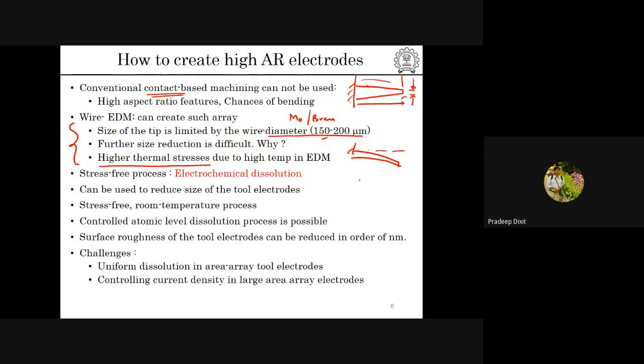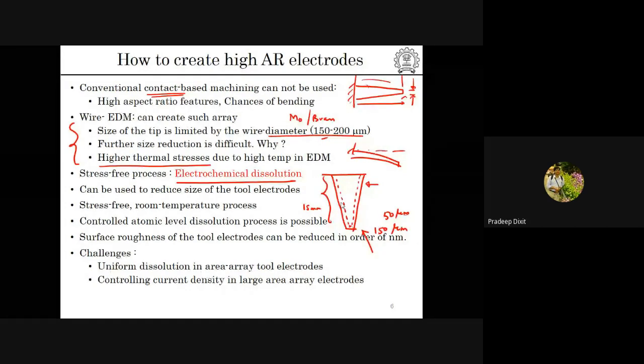So what we thought is that we will first get this kind of tool electrode by the wire EDM process, and then we will go for electrochemical dissolution. The idea here is that you fabricate the tool electrode. I'm just showing you a single tip. For example here, it could be 150 micrometer, and this could be 15 millimeter. After some point of time, if we do a controlled electrochemical machining and remove, let's say, 50 micrometer from each side, we will be removing this material by electrochemical dissolution, and we'll get a final tool electrode having the required dimension. So we try to do this combination of wire EDM plus electrochemical dissolution to get the required sizes.